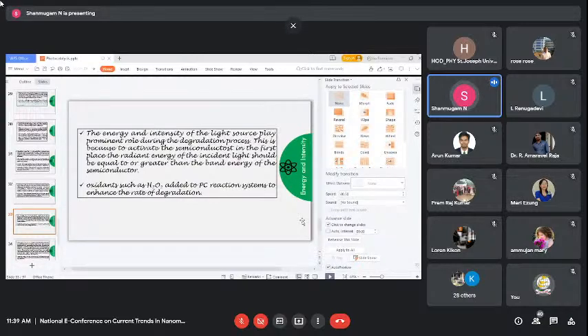We should provide some modification in the band gap energy, which means that we have to collect more and more photo charge carriers. The generated photo charge carriers are accumulated in different regions, different energy levels. We should not allow the charge carriers to combine. If they combine, the activity may be reduced. At the same time, we have to generate more and more photo-generated charge carriers. For that, we need high energy incident light. So the intensity of the light as well as the energy of the light are two factors which may enhance the catalytic activity. In that way, you have to choose.